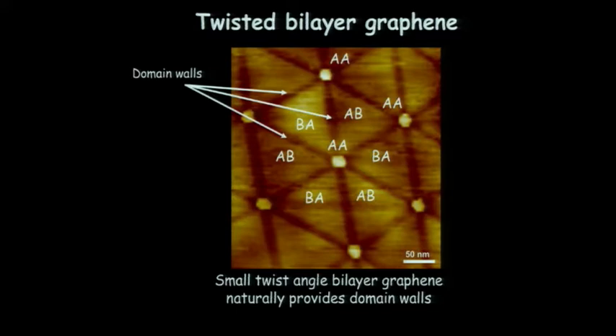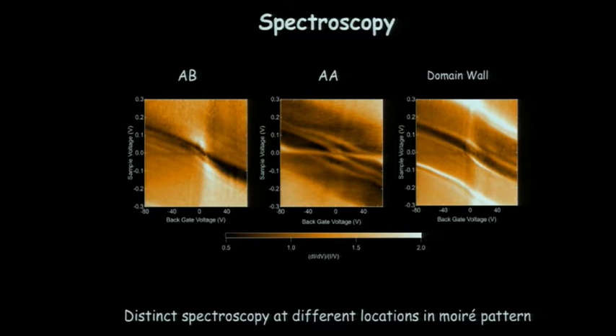So we went and did the spectroscopy around each of the different areas here. So you have AB, AA, and then this is along the domain wall region. And so what these plots are showing, the color scale is density of states. It's as a function of energy here, and then this is backgate voltage. So the backgate voltage is controlling the electric field in the sample, and the dark is low density of states, the bright is high density of states. And so what you see here in this Bernal stacked, we started basically at the charge neutrality point here. As we increase the electric field, this black region is getting wider in energy. We're opening up a band gap here at high gate voltage in the Bernal stacked. So the BA region looked identical to the AB, so I didn't show it here.